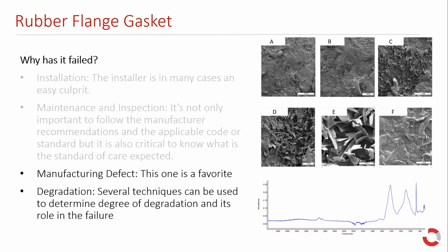Several techniques can be used to determine the degree of degradation and its role on the failure. In this particular case, the plaintiff's expert tested a sample from an area that was showing visible signs of what they consider to be degradation. The SEM images and the FTIR results that they presented are shown here and are great examples of the use of examination techniques that we discussed before.